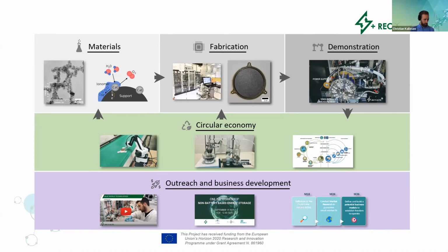And then we look at how to recycle the materials within the MEA, so we need to separate it before we can leach out the critical raw materials into solution, and we can then separate it using various methods, extract it, phase separate it, and then we can dry it, and then we have pure raw materials in precursor form that we can use for catalyst production again. And then you can see the loop.